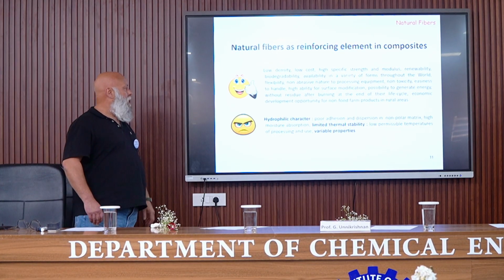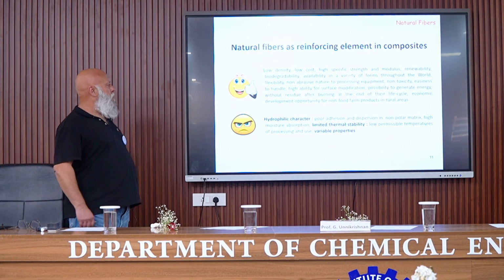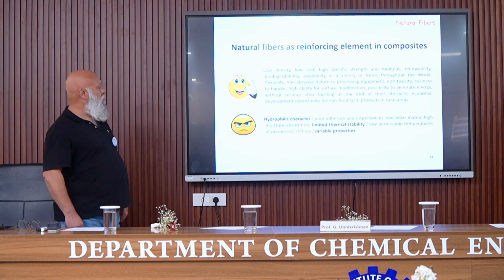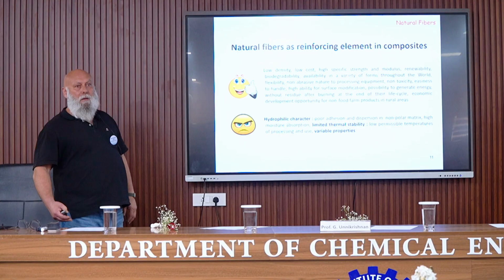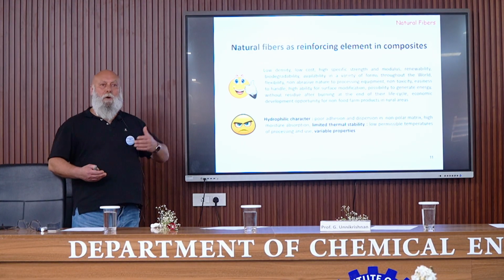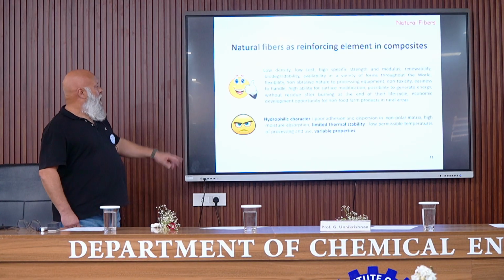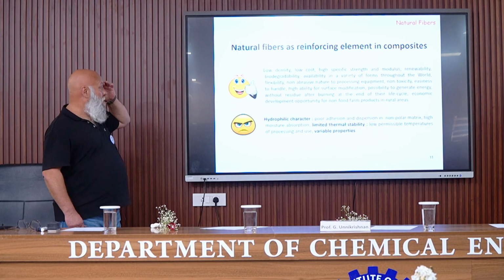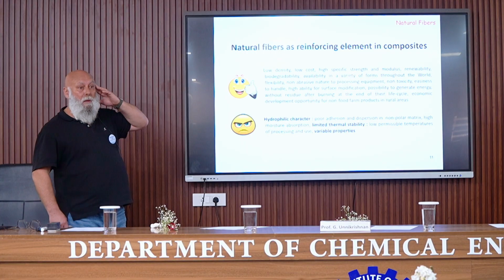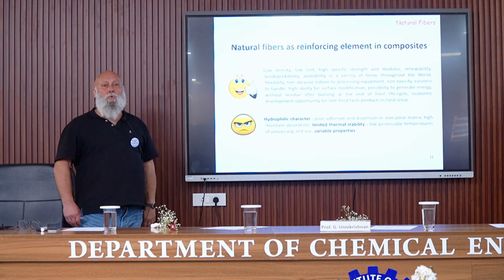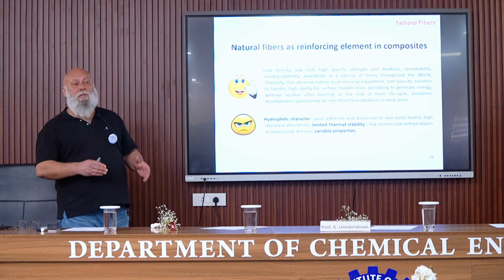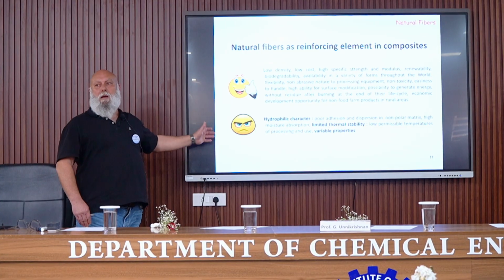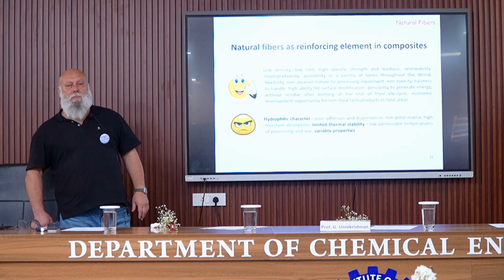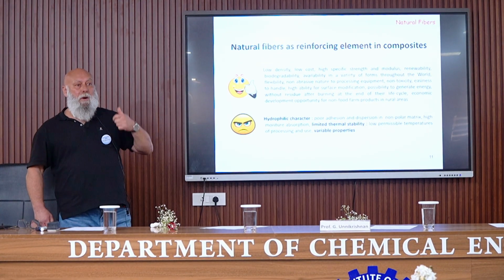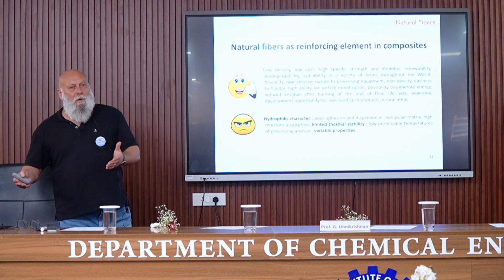The first one is linked to the hydrophilic character of natural fibers, mainly cellulose. It results in poor adhesion and poor dispersion in a polymer matrix that is in general non-polar. Like when you try to mix oil and water, there is a phase separation. High moisture absorption can also be a drawback. Limited thermal stability: in fact, cellulose starts to degrade around 200 degrees Celsius. So you cannot use this composite at high temperature, and you have to take care about the processing conditions. This is not really an obstacle, because most polymeric matrices can be processed at lower temperature, typically polystyrene, polyethylene, polypropylene, and so on, which is not the case for polyamide.